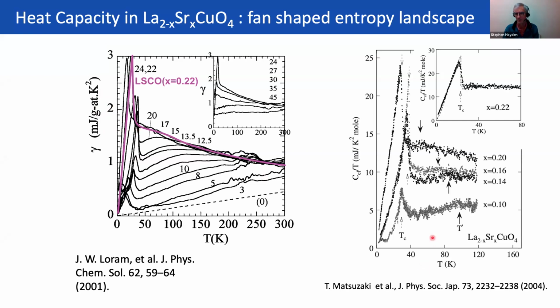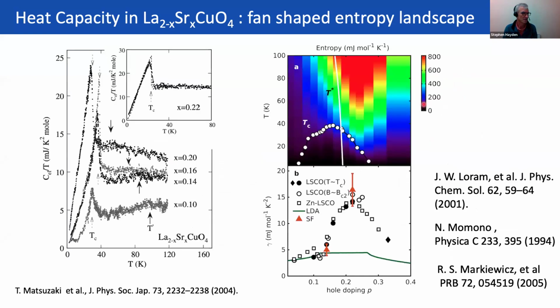But they are consistent with other people's data. Here's some other data just to show that this is consistent with this data. This is from a Japanese group, and you can see, for example, 0.22 is actually in this inset here, and there's quite a large specific heat at TC. So we have about 15 millijoules per Kelvin squared if you take the linear gamma, so C divided by T. Okay, so if you collect together specific heat data and you look at what gamma is as you vary doping, you can see there's a nice peak here around about 0.22 where the sample is. So it's got a relatively large linear specific heat.